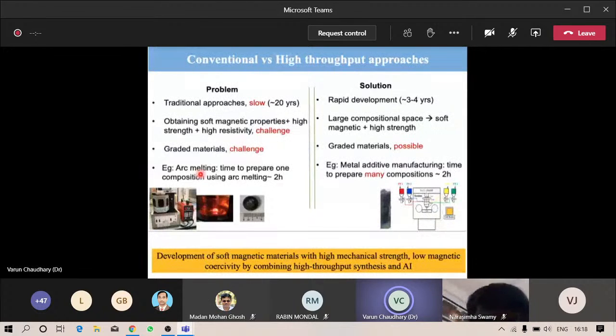As an example, arc melting and melt spinning, these techniques we use in the laboratory, take 1 to 2 hours to print one sample. On the other hand, with high throughput approaches, we can quickly measure a big composition space, and therefore there is the possibility to get an optimum composition for the properties we want. And there is a possibility to get a graded material using such techniques. So for example, with metal additive manufacturing, in 2 hours, we can print many compositions.